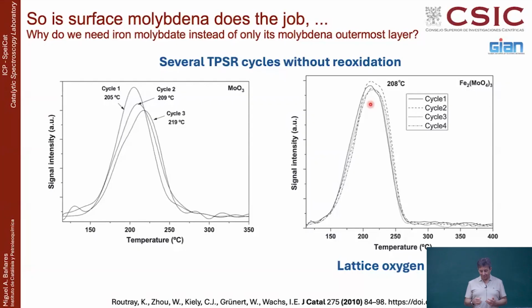How many cycles can you do? Not sure, but with time it will be affected. The point is, already with molybdenum, after 3 cycles you clearly see things going slower, while iron molybdate can take it quite well. So this is telling you about the mobility of the oxygen within the lattice.